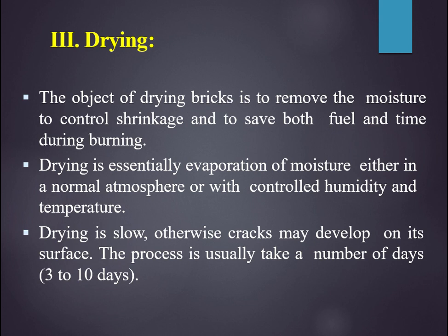These bricks should be allowed to dry, right? We will have around 30% moisture content in the bricks after the molding process. The main intention of the drying step is to remove the moisture content, right? We try to maintain the moisture level before going to the burning step. After the entire drying process is completed, we ensure that there is only up to 7% moisture content in the brick. Okay.